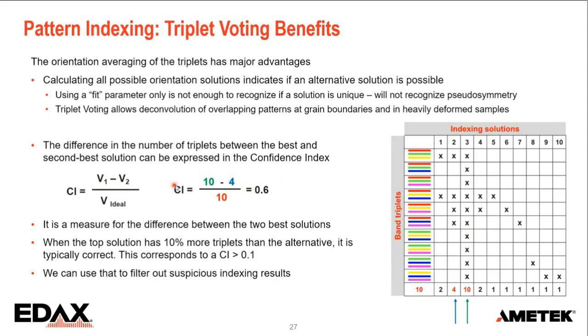And the CI, or confidence index value, in our experience, in most cases, when the best solution has 10% more votes than the second best solution, it's okay. So that means a confidence index threshold of 0.1. And that is something we use all the time to remove suspicious results, or, as I will show in a moment, to identify porosity.